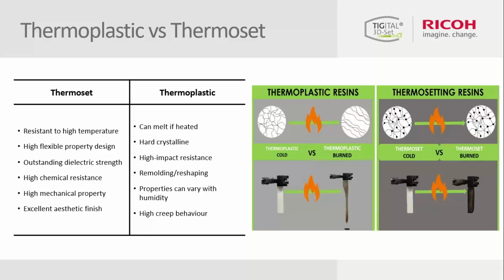What happens during the printing process with the laser used in SLS printing technology? The material is not directly melted; it starts to react with each other and with the other materials which come in touch with the laser. Based on this cross-linking, we can reach higher thermal stabilities compared to thermoplastics. Just one example: if you heat a completely cured Thermoset material up to 200 degrees, PA12 will start to melt, but the Thermoset material we are offering will just get soft. It will become like an elastomer, but it will not melt. The design which you printed in the printer will not change.